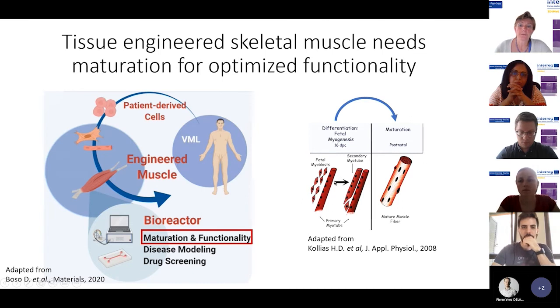This way, several of these fibers can be made, but they still need to mature into a real muscle fiber, which is shown here, in which the nuclei, depicted here as black circles, all go to the outside of the muscle fiber, and there is also a striped structure in the fibers, which tells us that they are functional, so they can contract. And this shift is quite difficult to make in the lab.